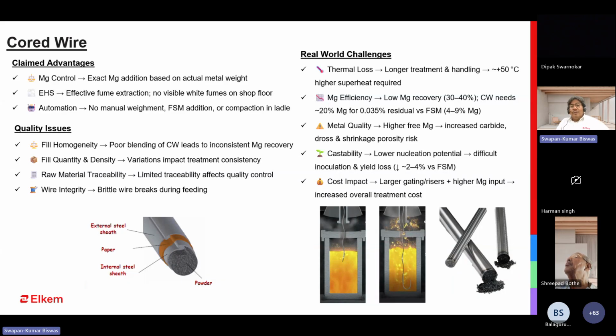So in cost impact, if you calculate with this process, whatever we have observed, customers are changing their gating systems. They increase the riser and runner to compensate for the micro shrinkage. That means they are compensating on the casting yield. So if you calculate how much I'm gaining with this magnesium treatment and how much I'm losing on the yield when you increase the riser and runner size, then you will get the real picture whether it is really beneficial or not.